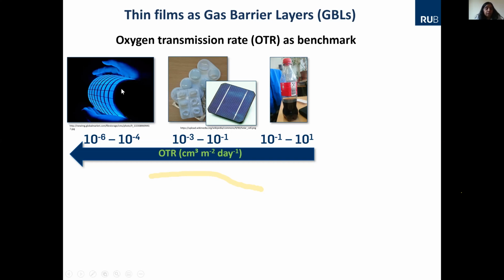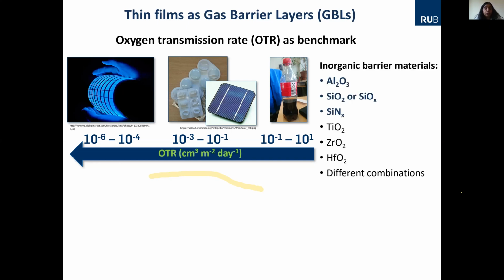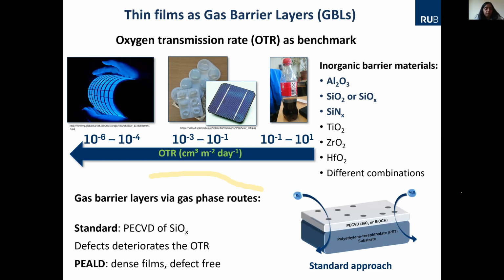And here you see there are many materials that can be used as barriers, for example, aluminum oxide, SiO2, TiO2, zirconium oxide, or you can use a combination. So if you take your PET bottle, your Coke bottle, it is actually polyethylene terephthalate, and then you have a thick layer of maybe 100 nanometers SiO2, which is done by CVD, plasma enhanced CVD. It serves the purpose because it's a fast method, it's cheaper compared to ALD. ALD is a very slow process, but very effective.